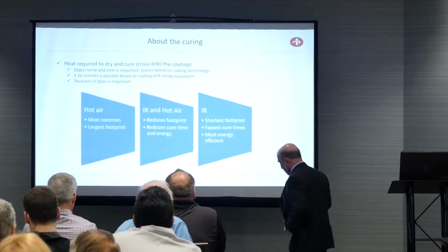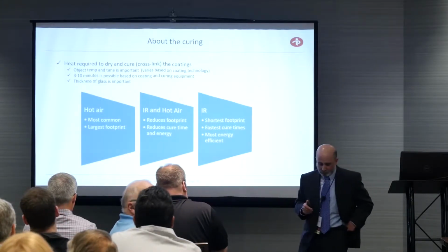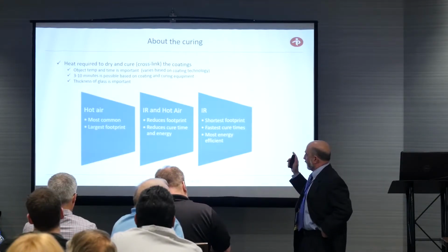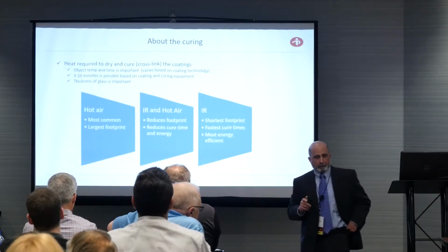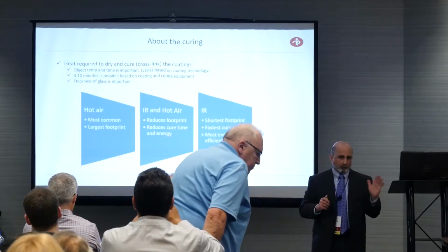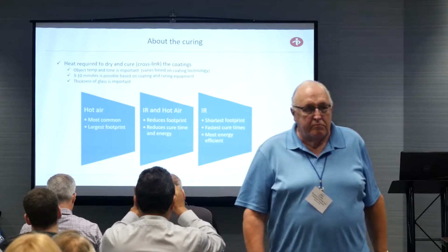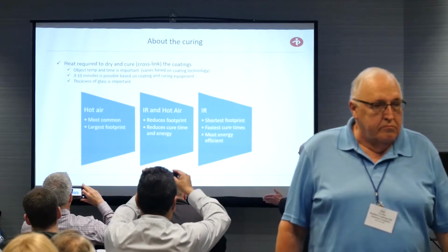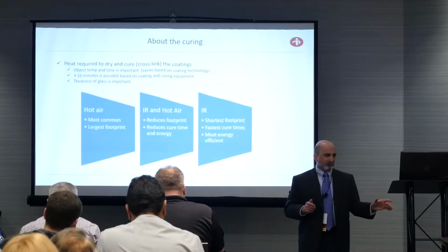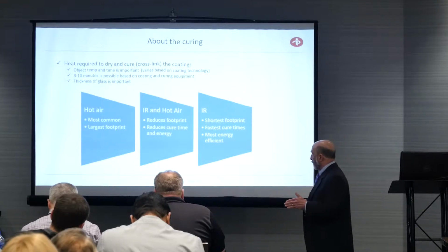Okay? Let's talk about curing, because this is an important link to what I'm seeing on trends in the industry. I mentioned earlier they all require heat to cure. I'm pretty sure we all understand there's a difference between drying and curing, right? These have to be cross-linked. It takes heat to cross-link them. Something can be dry, but it's not going to have the physical properties that we're looking for. It has to be cured to get the physical properties, right?